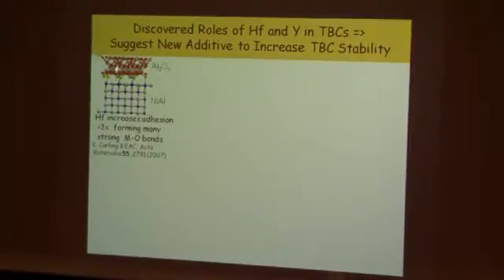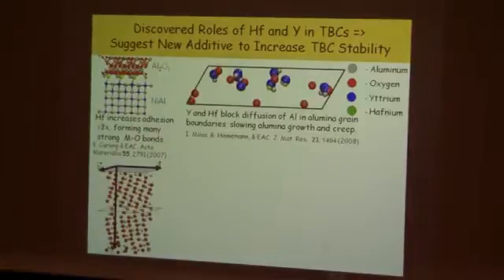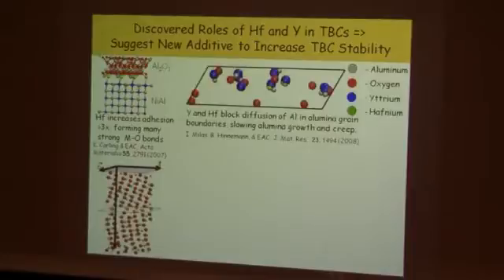And it turns out that hafnium acts like a glue. It loves oxygen so much that it just sucks up to the alumina oxygens and essentially improves the so-called adhesion of the ceramic to the metal. And that's one role that hafnium plays. So what we learned from that is that it's really important to think about what kinds of elements really love oxygen, because they actually may help stabilize the coating.